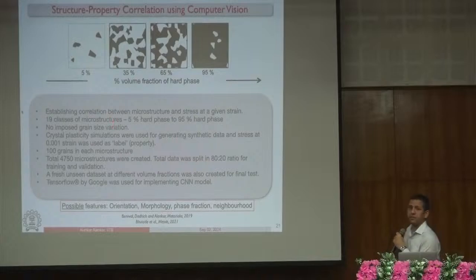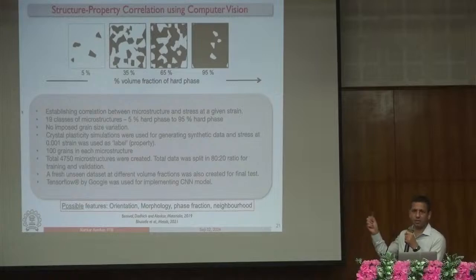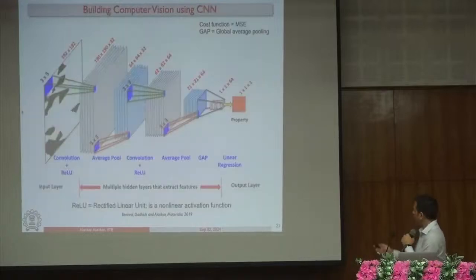So we set up a computer vision problem here by using a convolutional neural network, where each of these images is shown to a CNN network, right? And then you do several manipulations by choosing the number of layers, by choosing the type of convolution, by choosing the nonlinear function. We use ReLU here, but you can try many others. And then you try to relate this structure with the property, which in our case was modulus